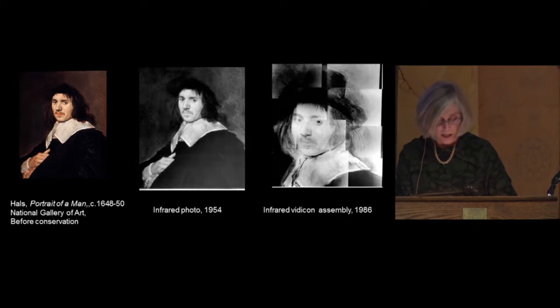a television screen. Because the thermal imaging cameras used for infrared reflectography are relatively low resolution, information can only be captured over small areas a few inches wide in sequence, and with the Vidicon system, image capture was a very slow process. To achieve a high-quality image, many individual captures had to be made over small areas of the painting, and later mosaicked together following an overlapping grid pattern across the surface. Hundreds of individual reflectograms might have to be collected to form one overall image if the painting was large. After capture, each individual image on the monitor screen had to be photographed, printed, and then assembled into the final mosaic, which was again photographed.